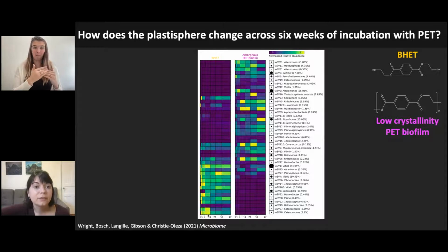And what we see is that for the low crystallinity PET, they're tending to be abundant at later time points. And that's probably just because it takes longer for them to even try to degrade the PET than it does for the BHET. And I also just want to highlight that some of the taxa that we're seeing here are within some of the hydrocarbonoclastic groups.